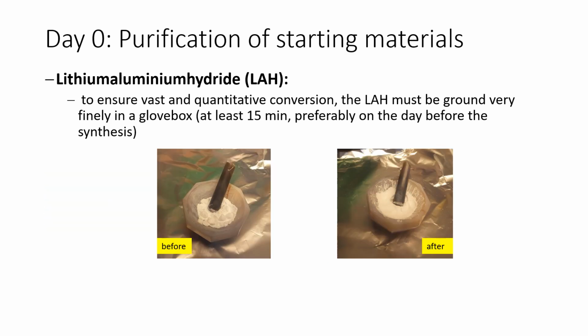When we have now obtained our very pure lithium aluminum hydride, we have to prepare it for the reaction. For the reaction to the lithium salt of the weakly coordinating anion, it's very important that the lithium aluminum hydride is a very, very fine powder. Hence, we should grind it for at least 15 minutes, preferably on the day before the synthesis, in a glove box. You should definitely only grind lithium aluminum hydride in a glove box because you will get hydrolysis outside the box, and also if you grind it in air, there's the risk of an explosion.